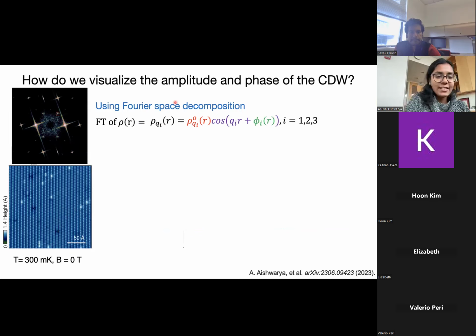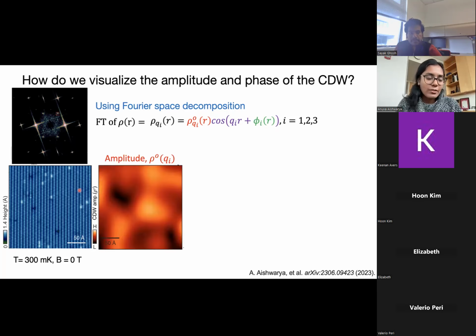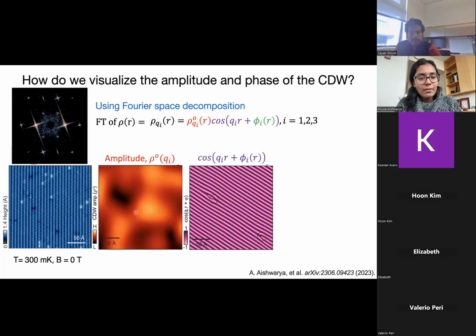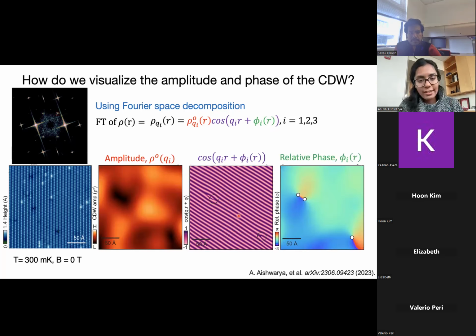I'll divide this into three parts. One is the amplitude, the other is the modulating component, and next is just the relative phase, where we remove the Q information. So the amplitude looks as so. And this is the modulating component where we see Q and phi. Q is the modulation wave vector and phi is the relative phase. And if you just look at phi, then you see something like this.